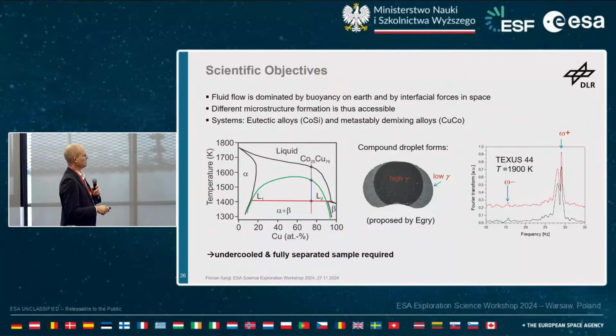So effectively, instead of getting the Rayleigh frequency, you have a split and you have 2 additional frequencies, omega plus and omega minus. The omega plus is pretty prominent, the omega minus is difficult to detect. But if you have this compound droplet, you should be able to get interfacial tension. The colleagues from Japan are working in the ELF facility on slag iron systems with an application in the steel industry to better understand slag iron interaction. Here you could do that in this demixing undercooled metallic system, but it requires a fully separated sample.